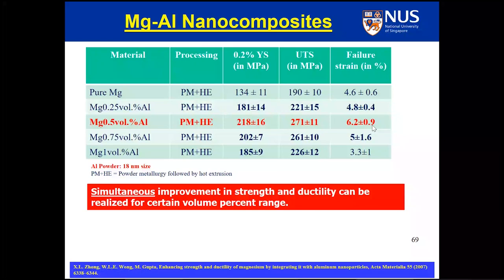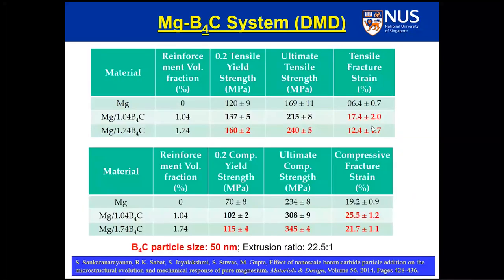You can also put in a ceramic reinforcement, like we put boron carbide in magnesium. If you look at the red fonts here, the last row with 1.74 boron carbide, again you are seeing an improvement in the strength, improvement in the UTS, and also a doubling of the ductility. If you want to triple the ductility to 17%, put in 1% of boron carbide. And not only in tensile properties, you can see a simultaneous improvement of strength and ductility in the case of magnesium. Not in all cases, but there are many systems which show this kind of simultaneous improvement.